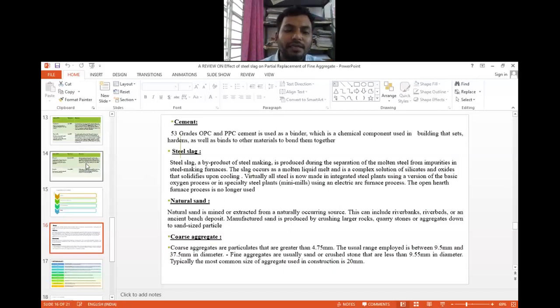Natural sand: we are under the zone 3 category, so we use zone 3 natural sand. Next, coarse aggregate. In our area, coarse aggregate means particles from 4.75 mm to 37.5 mm. In my research, I use 20 mm steel slag as my coarse aggregate.